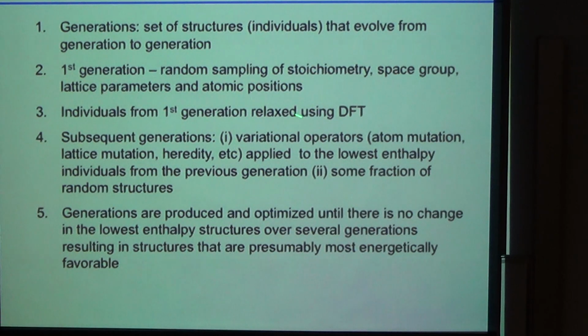Then you take this generation and relax using density functional theory at a given pressure. Pressure is fixed, volume is relaxed, so you optimize the lattice completely. You change the bond lengths, lattice parameters, angles, and so on and so forth. Actually, the space group is not fixed because it automatically comes out of the calculation. Once you relax the first generation, you classify the structures based on the energy, actually enthalpy, because the PV term at high pressures, at 100 GPa, is extremely important and gives a substantial contribution to the energy. So we work with the enthalpy, so it's energy plus PV.